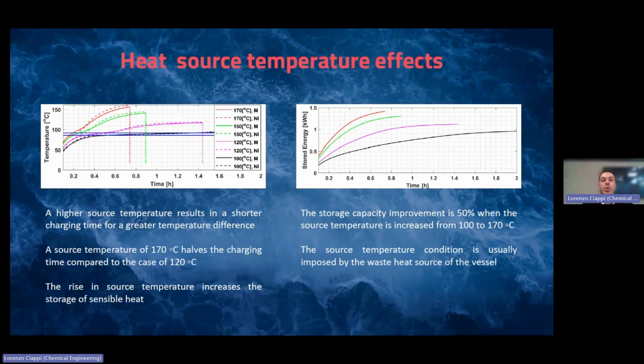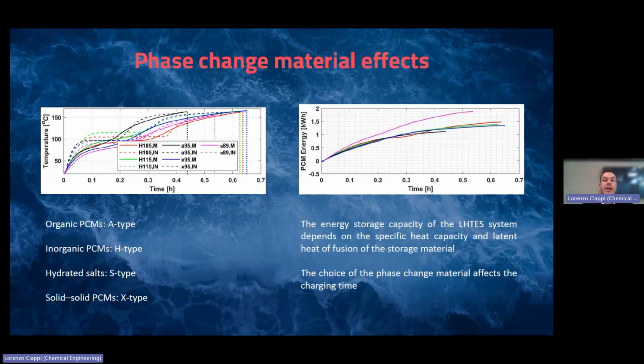This is mainly due to a higher heat transfer, and in particular, the higher energy that is stored is connected with a higher value of the sensible heat below the level of the melting temperature and above the value of the melting temperature of the PCM. The choice of the phase change material is a significant parameter. Indeed, the phase change material has to be selected based on the application case. And we can see from the analysis that was conducted that the specific choice of the PCM strongly affects the dynamics of the charging of the system and the energy that can be stored by the phase change material itself.